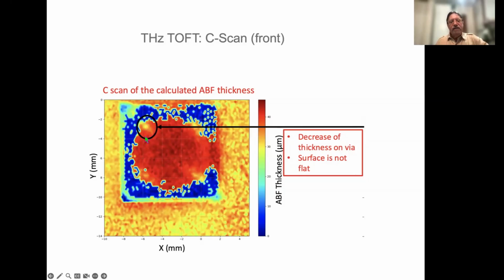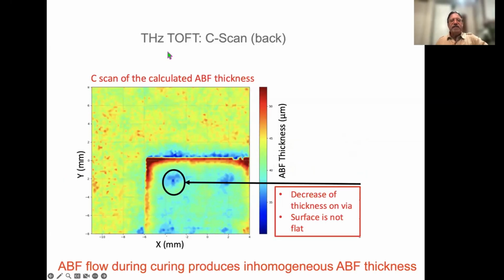For example, over the vias in the die, excuse me, the ABF film is thinned as well as around the edges of the die. So what happens, we think, is that as the ABF is cured, there's some flow of the ABF into those gaps, whether they're vias or around the die, that produce a thinning of the ABF. This also occurs on the backside of the same structure. So this is an interesting sample.